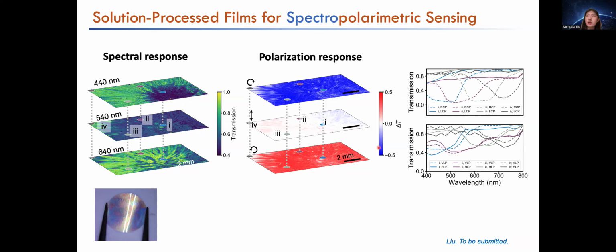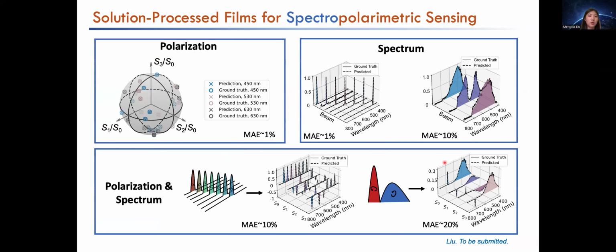And it turns out to allow us to get very different transmission spectra for different polarizations, and we finally make this into a spectral polarimetric sensor. Under a single wavelength and uniform polarization, we are able to accurately resolve the polarization state. And also under a uniform polarization, for a given spectrum, we can accurately reconstruct the spectral information.